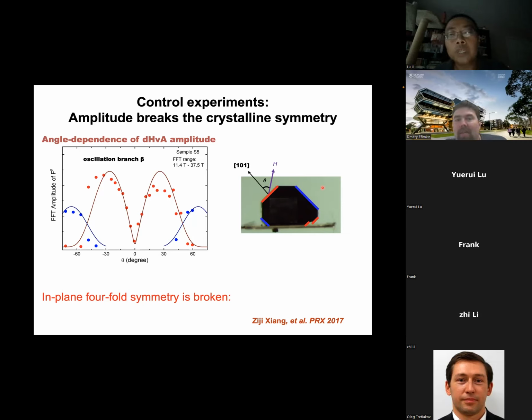Now, if everything is determined by the simple bulk, how would we have a large oscillation amplitude, which suggests a lower disorder level along one axis? Then the other one would be more disordered. Why would disorder have an orientation preference? This way is better than the other way. That made us still hesitant to think this is a completely bulk phenomenon.